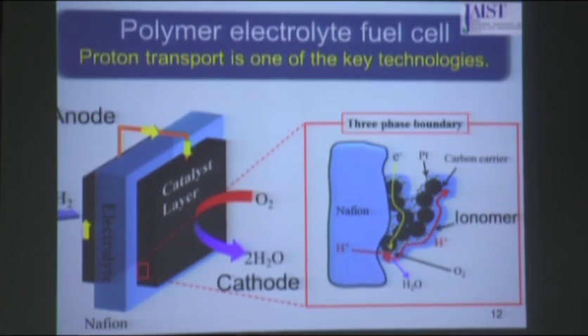So proton transport is one of the key technologies. Proton transport is used in the electrolyte, this blue region, and you see that this is the magnified three-phase boundary. That is the reaction site of the fuel cell. The white one is the platinum electrochemical catalyst, and the blue one is the polymer proton exchange membrane, normally Nafion, so we use it. I will introduce it later. This is the membrane electrolyte, and here is the ionomer. This is also Nafion, but it has quite different properties. But anyway, proton transport is one of the key technologies.